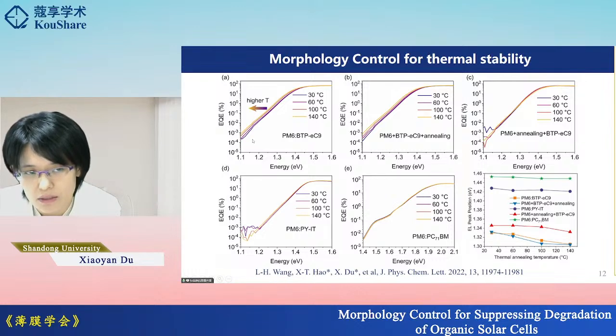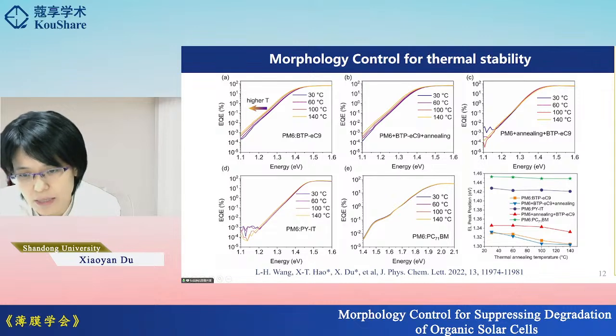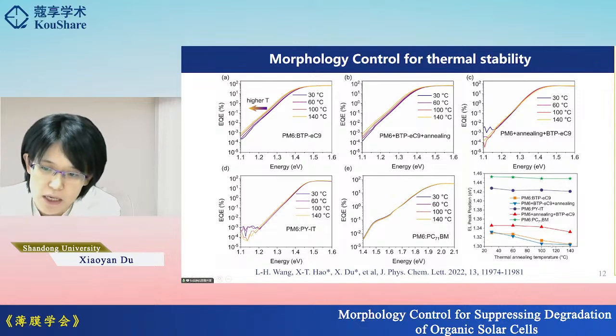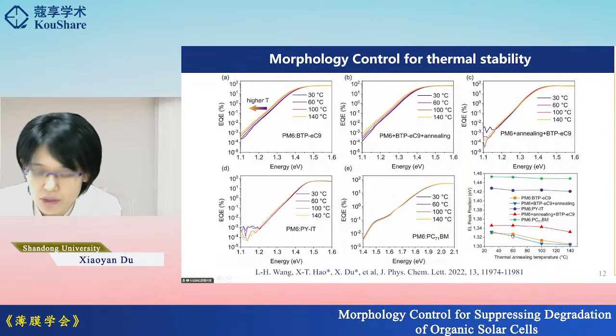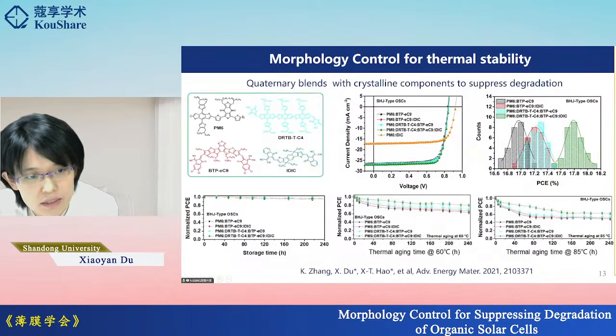For example, in this sensitive EQE here, this blend based on the non-fullerene acceptors is easily changed or modified by thermal annealing, and also in the emission, in the electroluminescent spectral peak position. Based on the non-fullerene acceptors, it's more readily modified. And this slide shows the reasons for decreasing VOC in organic solar cells, actually, but I'm only talking here about the thermal stability of devices.